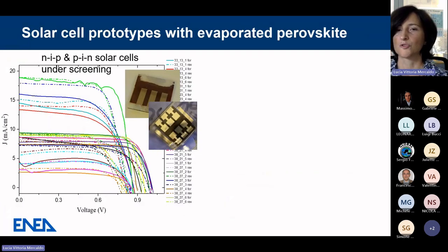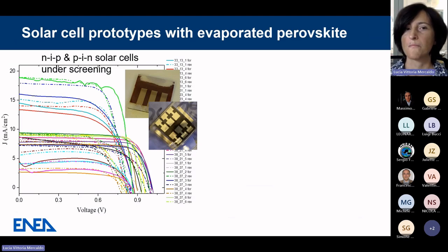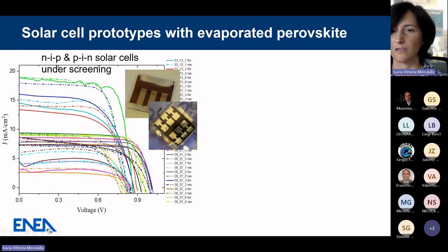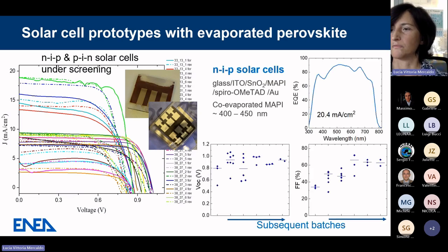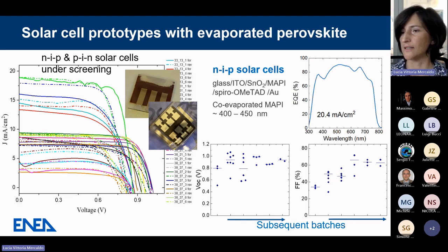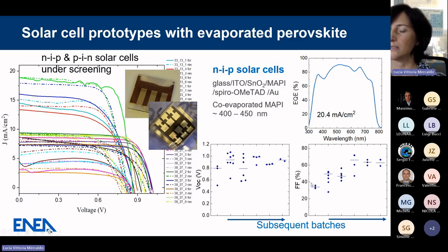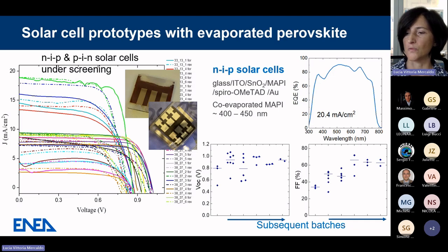And in this slide, I'm showing several PIN and NIP solar cells that are under screening with various designs. These are pictures of lab scale designs implemented in our lab. And here also some results about the NIP solar cells with co-evaporated MAPI, methylammonium lead iodide, and the evolution that we have with subsequent batches down here. So as long as we understand better and better the deposition conditions, we improve the quality of our devices.